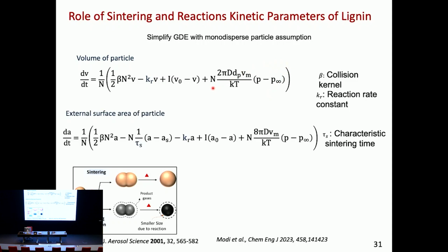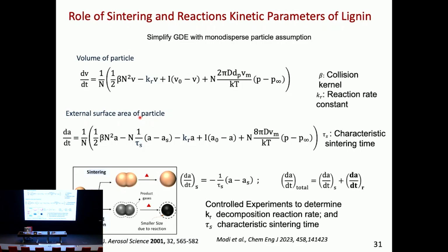Now, to solve this, I really need to track the surface area because the sintering is driven by the surface area. So I similarly have an equation for the surface area of the particle. Again, similar terms, but now I have a sintering term which tends to reduce the area towards a spherical shape, and I have all the other contributors. So these two take place simultaneously. I need to really understand the sintering constants, the decomposition rate. I don't even have expressions. So I need to do a set of experiments to pull these values out.